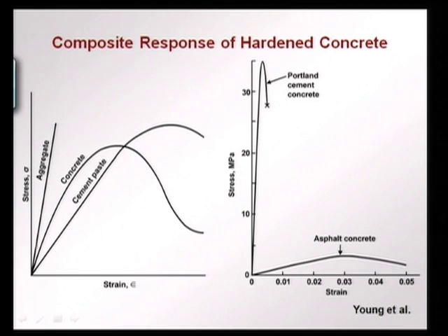So, this would be the stress strain behavior of concrete in usage. The cement paste on the other hand varies in properties, and it could have much less stiffness and also a non-linear behavior. Concrete shows a composite response, something between that of aggregate and cement paste, and depending on the amount of aggregate we have a behavior that is closer to the aggregate initially, followed by a non-linear response. So, concrete is a composite response that is derived from the response of the aggregates and that of the cement paste.